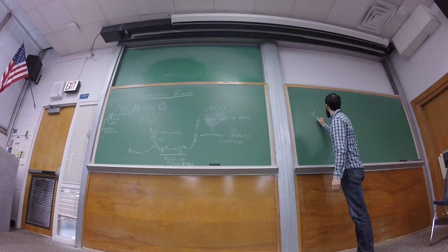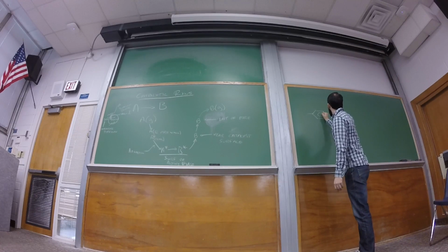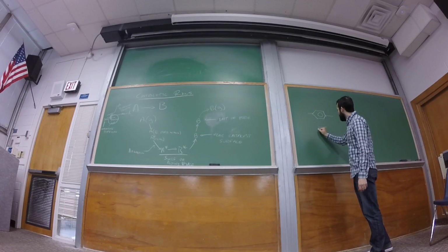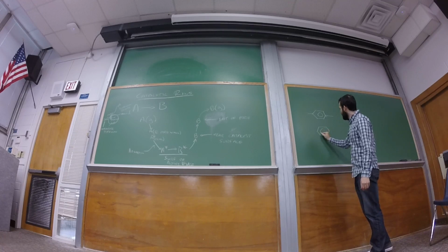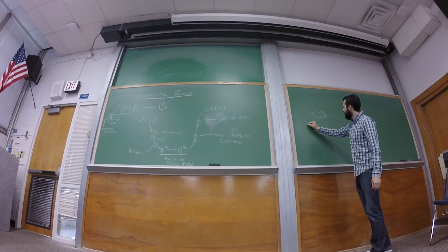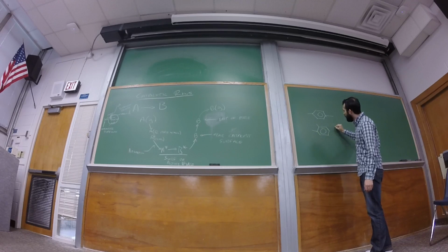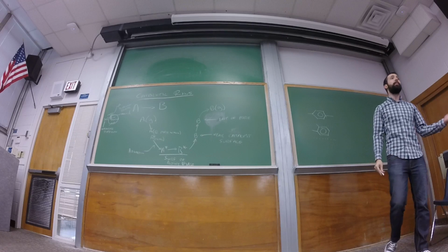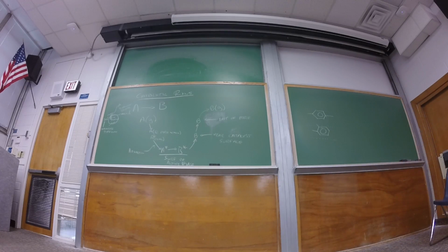One of them, it looks like this. So which one is that? And this one is harder to fit if I have a very tight pore. And so I can actually do this type of chemistry where I make xylenes, but only of a selective type. And then on the same token, you have product selectivities, because some things you make inside the zeolite, but they get trapped there. They can never leave. And it actually leads to catalyst deactivation, because you made something too big that can never escape.